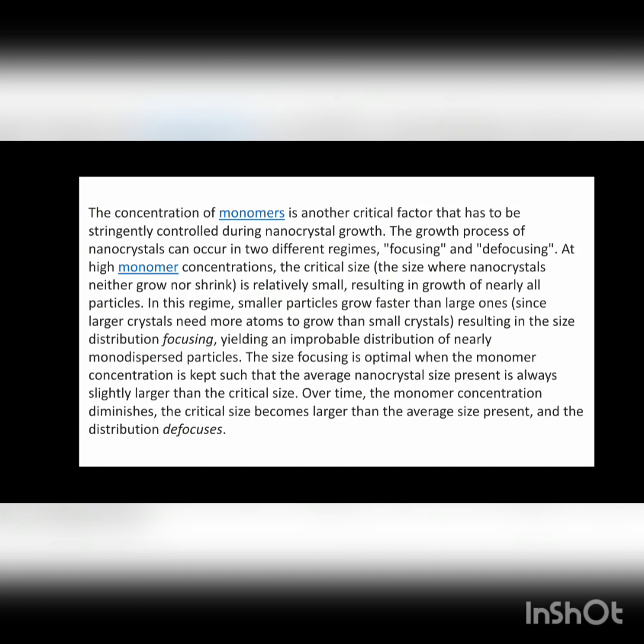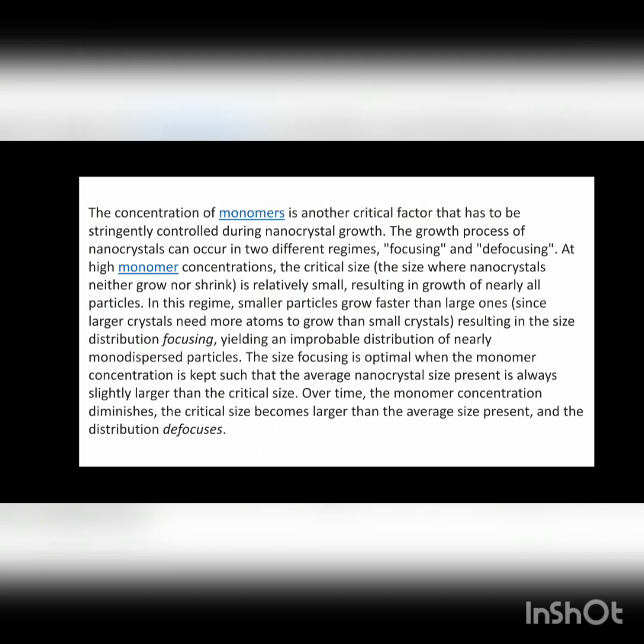The growth process of nanocrystals can occur in two different regimes: focusing and defocusing. At high monomer concentrations, the critical size is relatively small, resulting in growth of nearly all particles. In this regime, smaller particles grow faster than larger ones, resulting in the size distribution focusing, yielding a distribution of nearly monodispersed particles. The size focusing is optimal when the monomer concentration is kept such that the average nanocrystal size present is always slightly larger than the critical size. Over time, monomer concentration diminishes, the critical size becomes larger than the average size present, and the distribution defocuses.